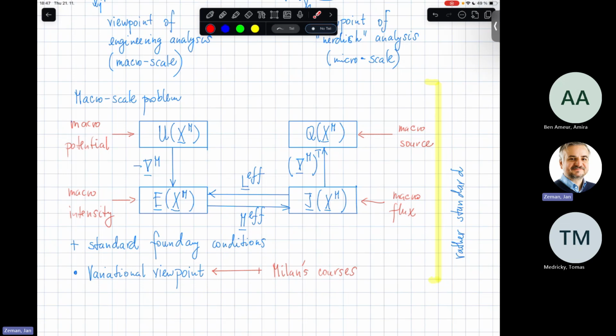So this is the justification of using, for instance, some models of elasticity, and anisotropic elasticity in particular, for analyzing, let's say, wooden structures, because these anisotropic coefficients reflect the microstructure which is beneath, and this is precisely what you do, right?